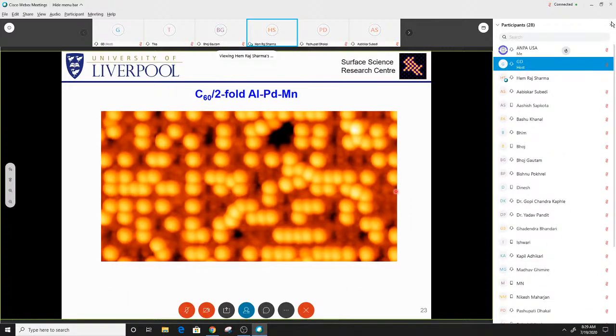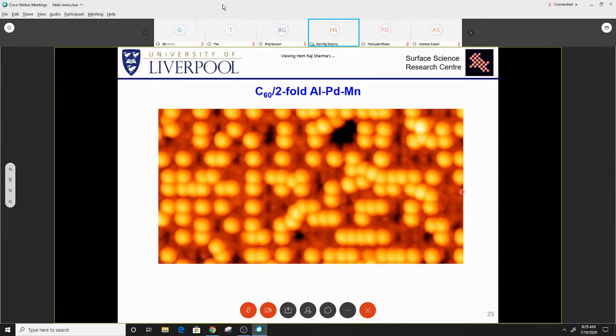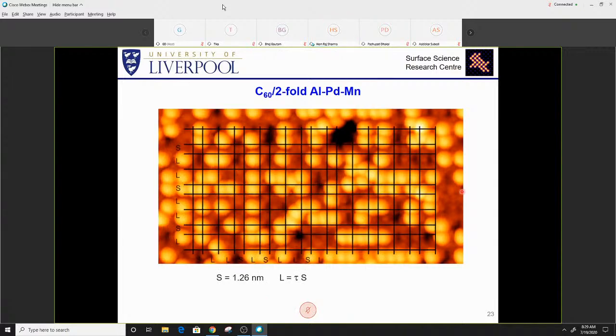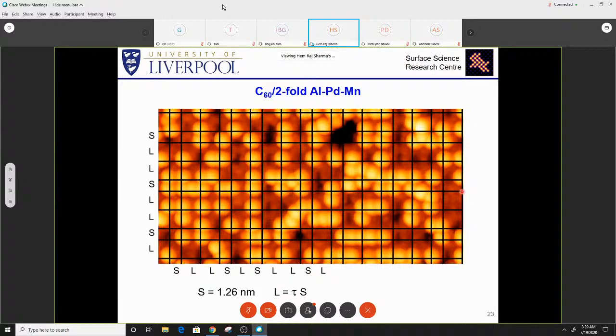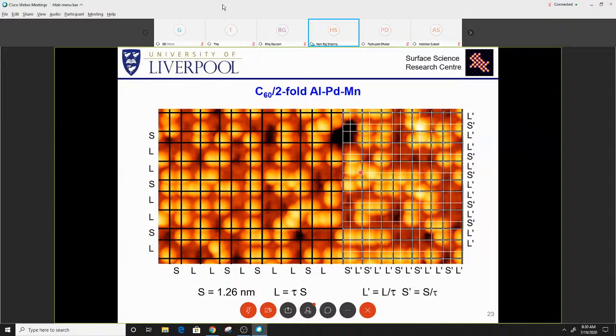Again, this is an STM image taken of a C60 covered surface. This sphere corresponds to C60 molecules. The C60 molecules are located at the vertices of a square frame this time. But you may see that some molecules are not aligned. But if you reflect your Fibonacci pattern, then you find all of the C60 molecules. So again, here are the scaling factors.